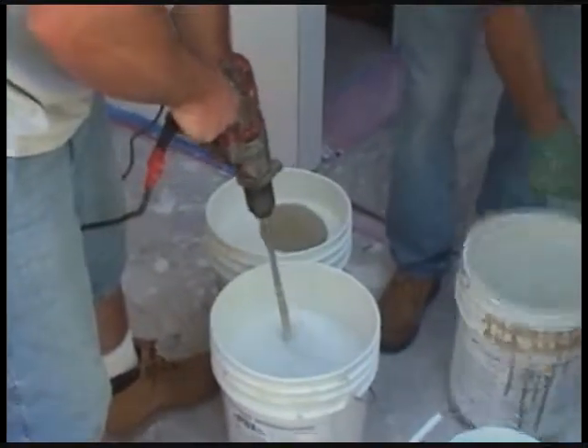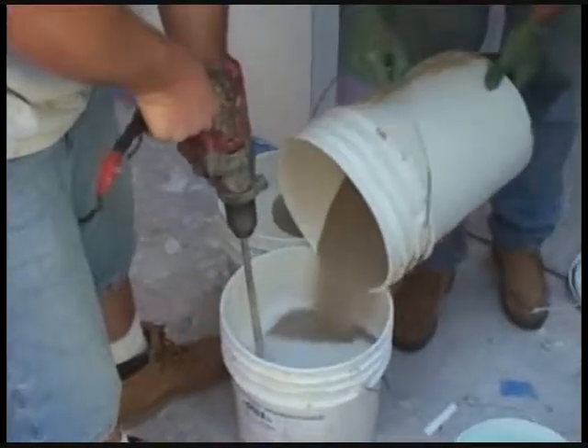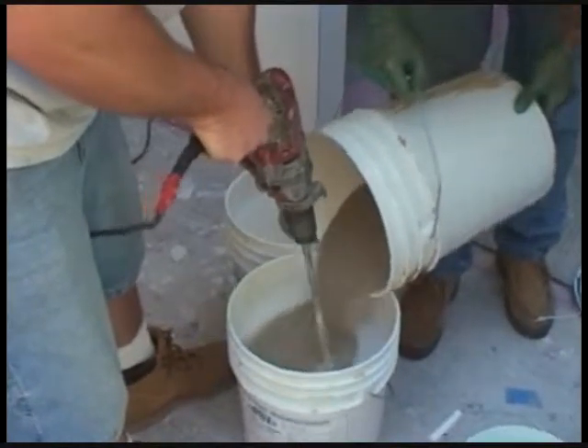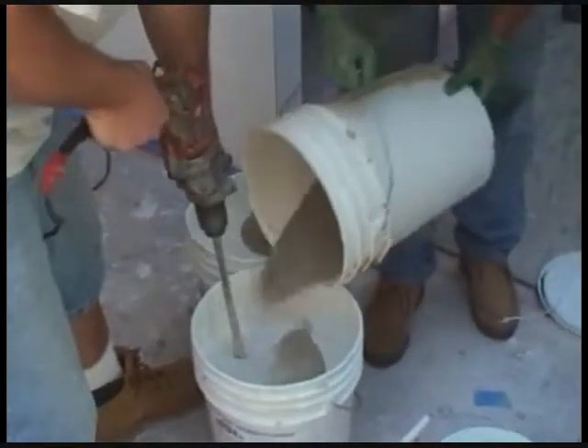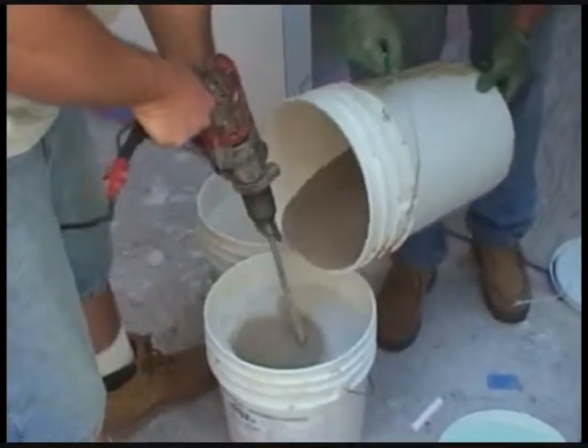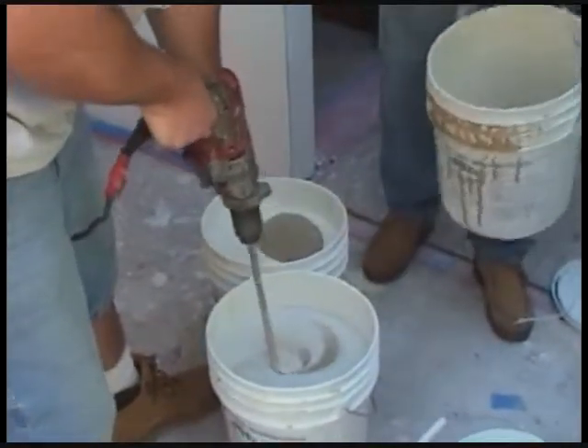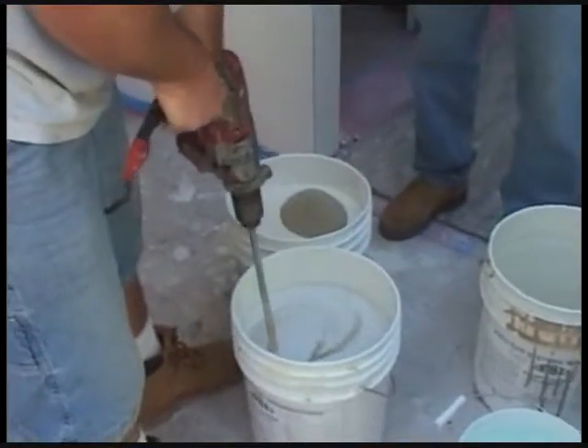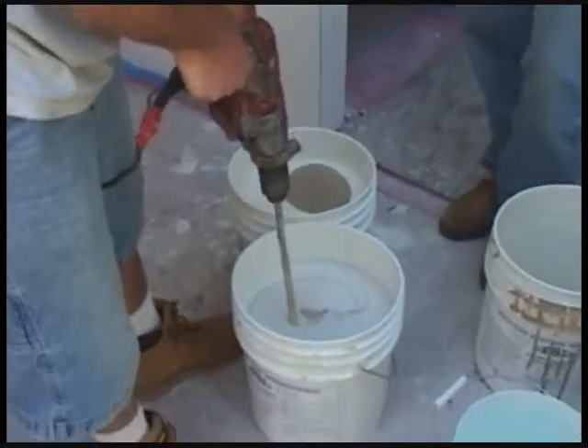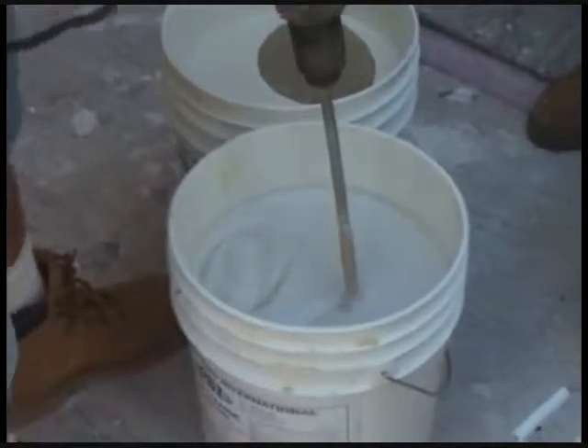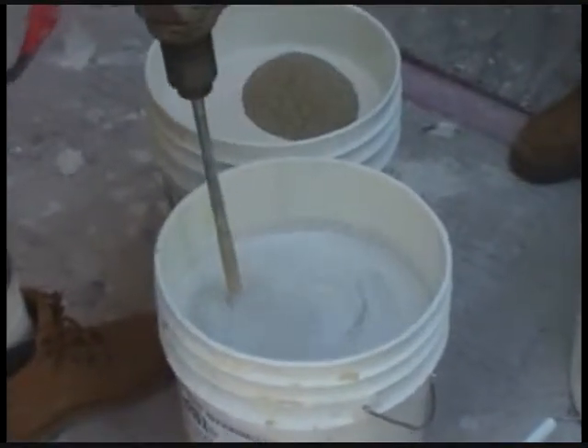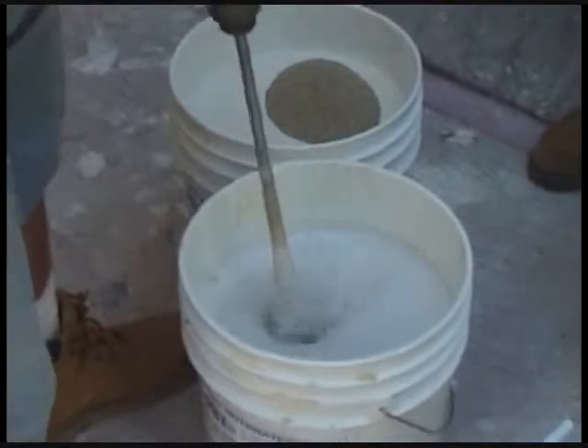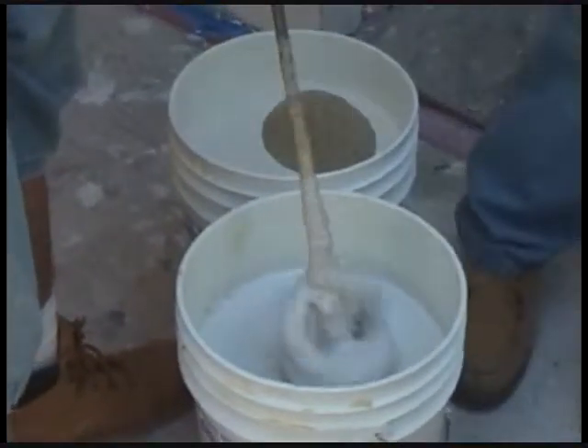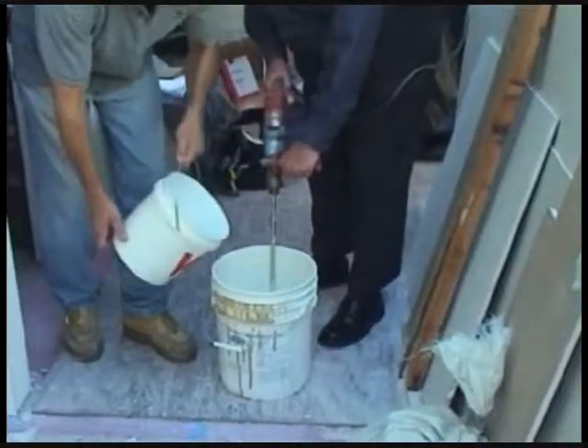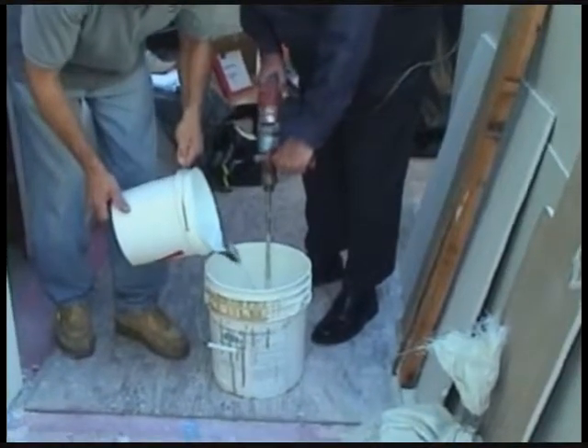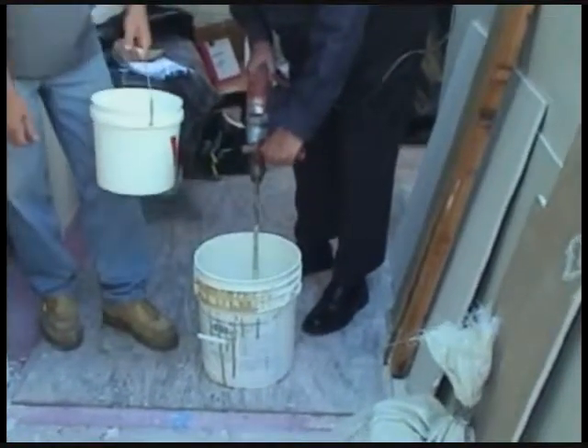When the sand is evenly dispersed, it is suitable to begin the trial application of the coating. You can see that after the sand is poured into the coating and mixed together, the slurry is still quite fluid, even though it has 2 gallons of sand mixed into the coating. It's important to keep the blade under the coating when mixing, and don't forget, it's 2.5 quarts of water to 2.5 gallons of coating.